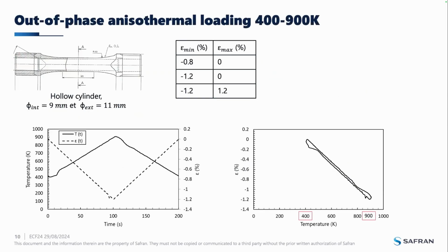Due to the loading in the structure, I also conducted out-phase anisothermal loading between 400 and 900 Kelvin with hollow cylinders. So when the temperature rises from 400 to 900 Kelvin, the mechanical strain decreases, and when the temperature decreases, the mechanical strain increases. So in this graph, you can really understand that it is an out-phase anisothermal loading.